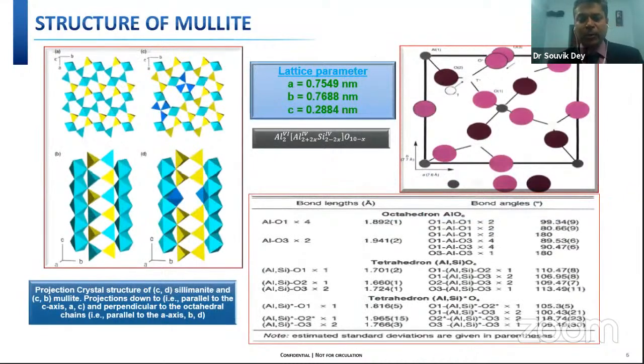This is the typical mullite structure. The structure is basically orthorhombic. It's an analogous structure with sillimanite, the space group is Pbam, and the crystal structure of mullite is Pbam. The backbone of the structure is, as in sillimanite, mullite consisting of edge sharing AlO6 octahedra, forming chains running parallel to the c-axis.